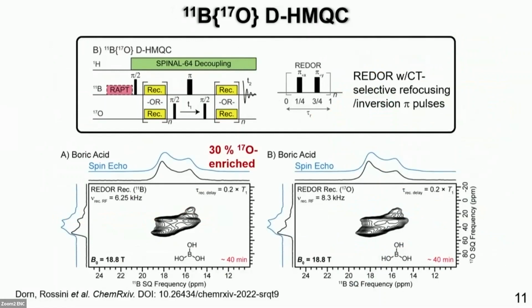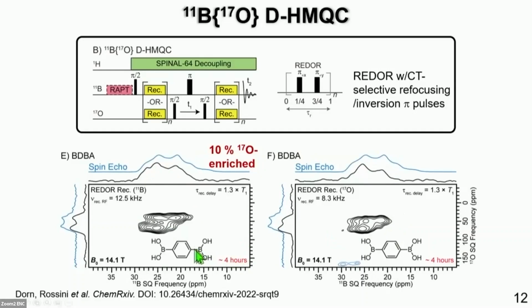We then recorded 2D boron-oxygen D-HMQC spectra. And here are two examples of 30% labeled boric acid at 18.8 Tesla with the recoupling either on the boron channel or the oxygen channel. And these spectra took about 40 minutes to acquire. We also did this for benzene diboronic acid that was 10% oxygen enriched at a lower field of 14.1 Tesla. And these spectra took about 4 hours to acquire. Now, the reason why a lot of these spectra actually took so long to acquire is because the boron T1 is actually on the order of about 10 to 20 seconds.